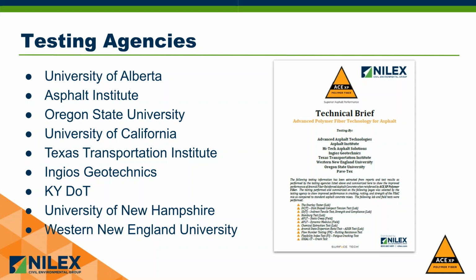Okay, great. And maybe one last question before the hour is up here for you, Michael. Using AASHTO, we apply a structural coefficient of 0.4 for asphalt concrete in structure thickness design. Using these fibers, has there been any research done to increase the structure coefficient? Great question. Yes. A lot of the field testing that has been done is actually back calculated out the in situ layer coefficients of the asphalt layers. And specifically for an AASHTO 93 model, you can take your 0.4 or 0.42 and increase it by 30%. That's probably conservative, but stick with no more than 30%. So your 0.4 is going to go to 0.5, 0.51 with that sort of layer coefficient. It's come out of the actual field testing that we've done.